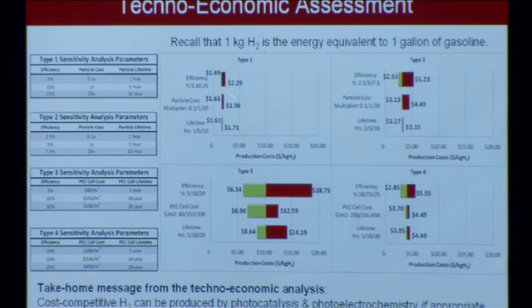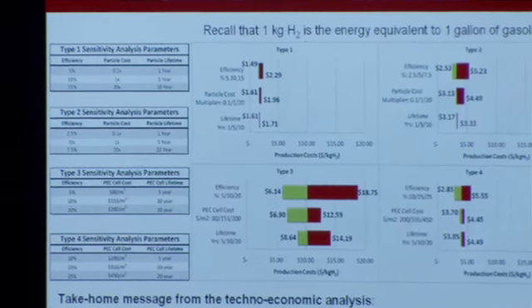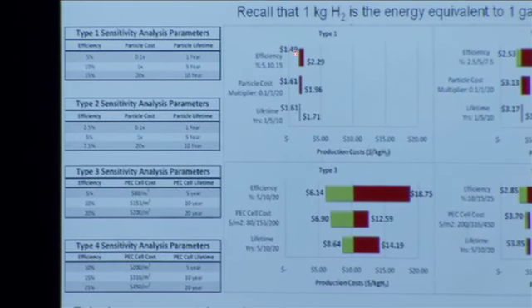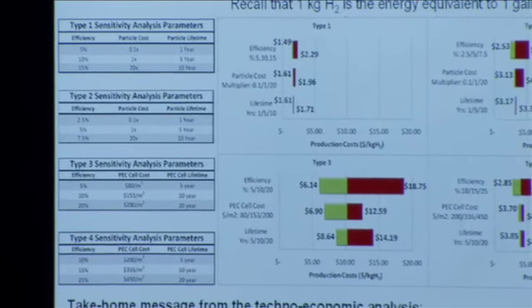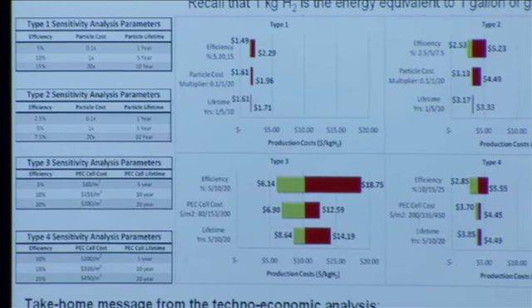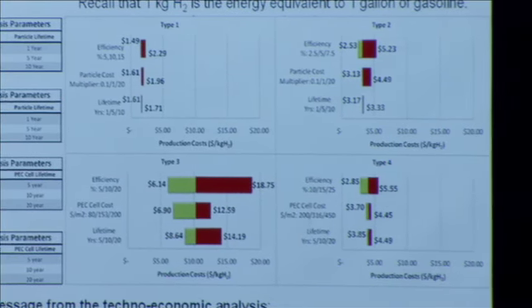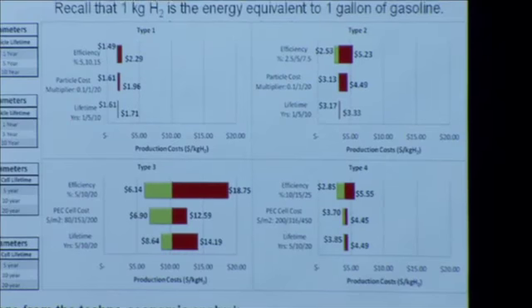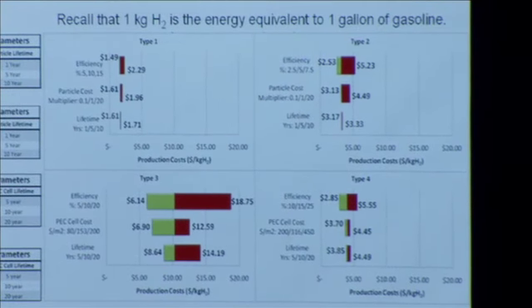And the first thing, we're looking at the type 1, type 2, type 3, type 4 reactor configurations. And I'd like to point out from a bird's eye view, first of all, you can see numbers as low as $1.49 and numbers as high as $18.75. Okay, that's a pretty reasonable range to be in, all right? We don't want to be paying $20 per gallon, but the $1.49 looks pretty decent.